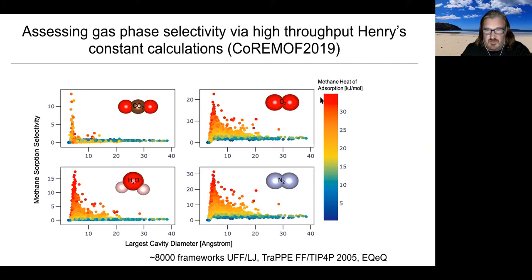We also colorized the structures for the heat of adsorption for methane. So you can see that selectivity is very much correlated with high heats of adsorption and relatively small cavities within the structure. I can't show it now, but in fact, we have the capability to hover over each of these points and interactively identify which of the reported crystal structures these map onto. So we can quickly identify a promising structure.